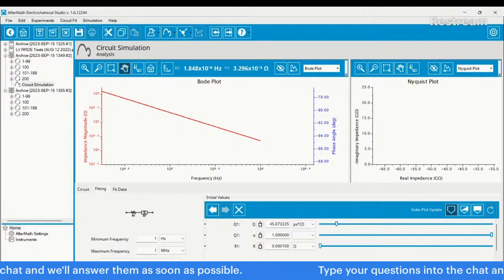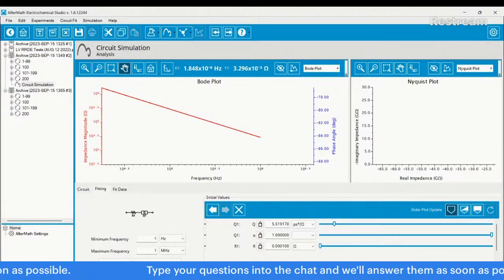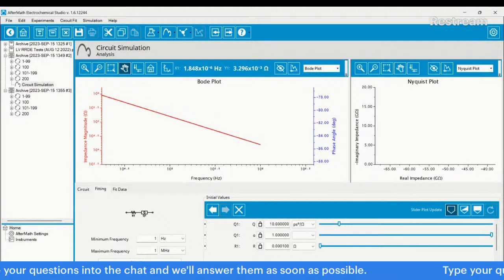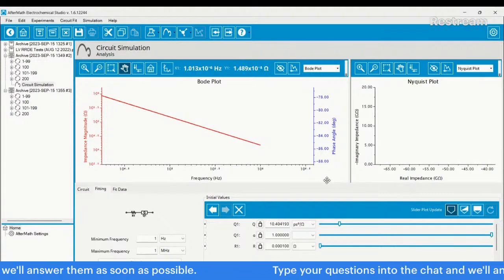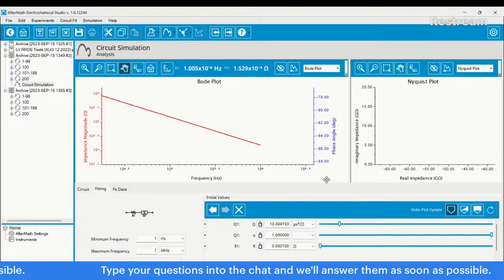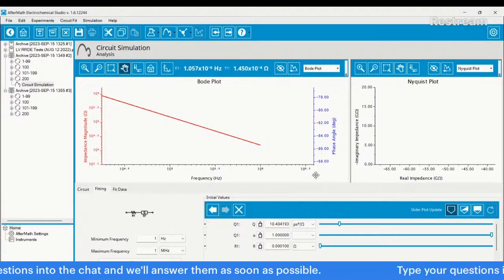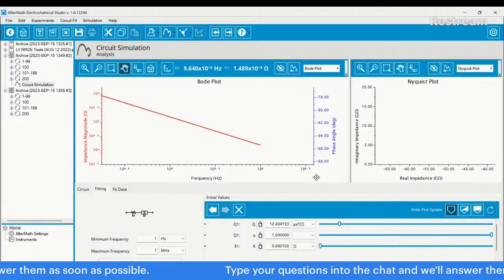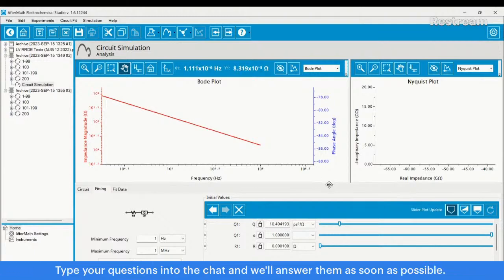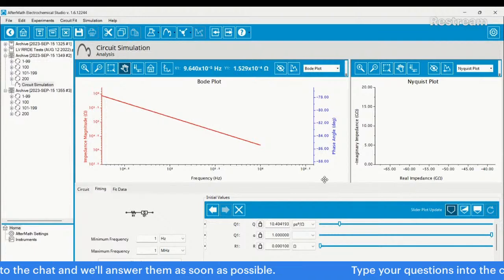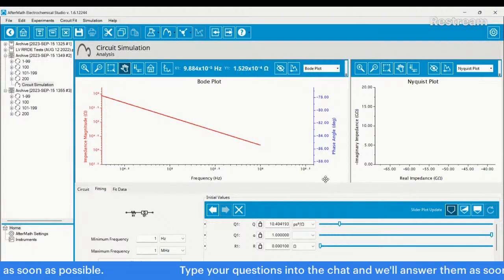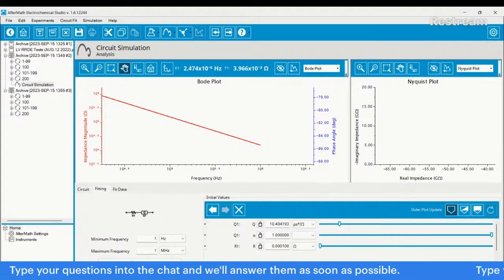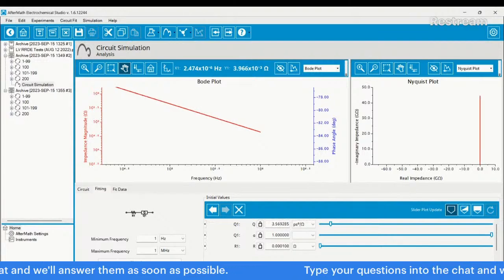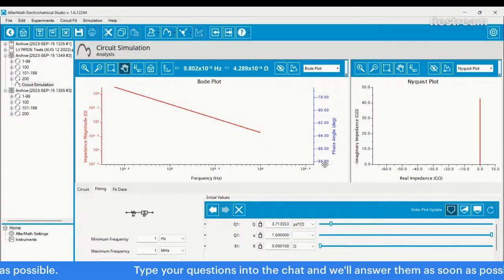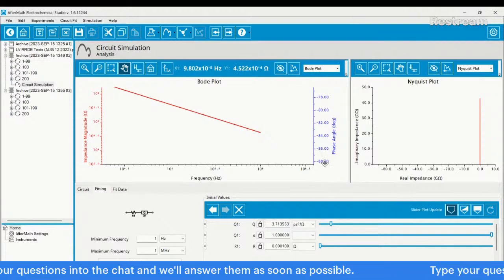So here basically is the plot, at frequency. As I increase the capacitance, it is an inverse relationship. So if I go to like 10 picofarads for some normal depth, I'm at 10K. So this is where the artifact basically comes from, in theory. There's a short range of frequencies where I'm at 10 kilo ohms or even slightly less, depending on how high of a frequency I go to. And I could be less than the frit impedance for some period of time. If I were to cut this in half and go to 5 picofarads, let's say I make really thick glass, I'm already starting at 40 kilo ohms. That's probably higher than the frit. So in theory it's not going to affect my results too much. So that's the point.